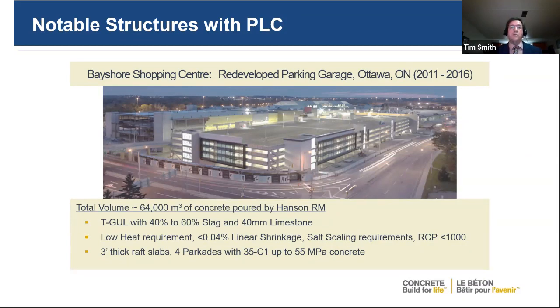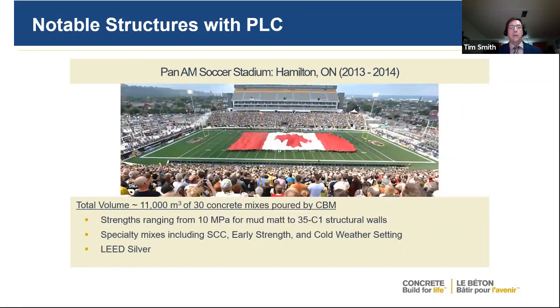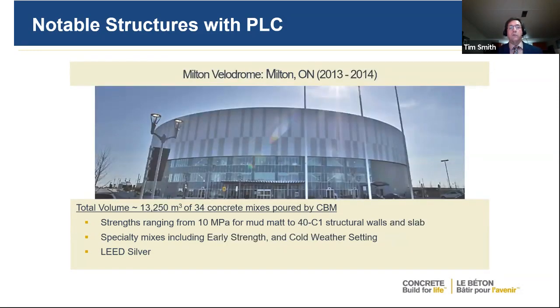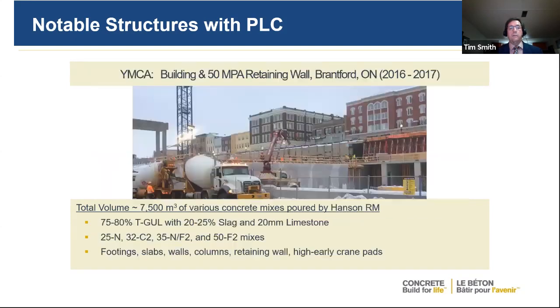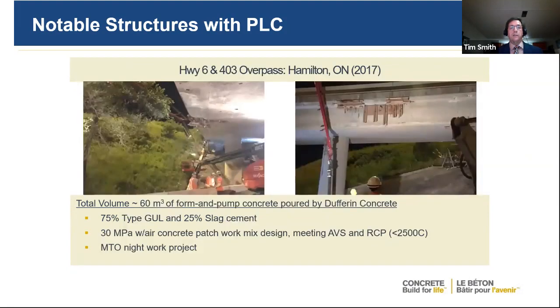So there is a long history of the use of Portland limestone cement. There's the Pan Am Soccer Stadium that placed 11,000 cubic meters of it. And you'll see in these cases, a lot of times they'll actually include the supplementary cementing materials in the mixes as well. Other ones, Milton Velodrome, 13,500. You get the YMCA building in Brantford, another 7,500 cubic meters. You see this time they used 25% slag in the mix as well, along with the GUL. So again, reducing that carbon footprint for that project.